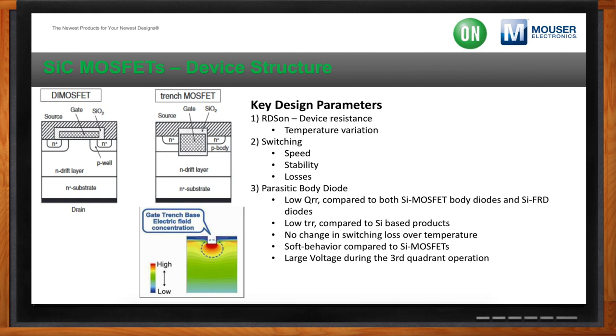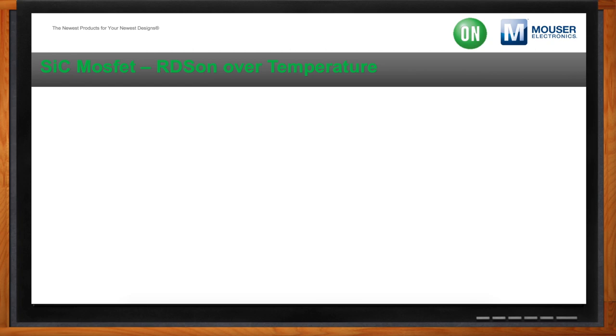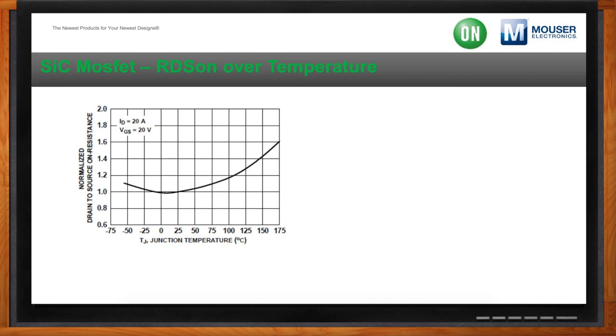Right. Okay. So let's talk about that first thing on your list, device resistance. Yeah. One of the neat things about silicon carbide is that when you take a part that has a resistance of, let's say, 80 milliohms, and run that from minus 50 C up to 175 C, we only get a 1.6x shift in RDS on over temperature, whereas compared to silicon, it can shift up to 2.5 times as much. Wow. So over temperature, you get much tighter control of your device.